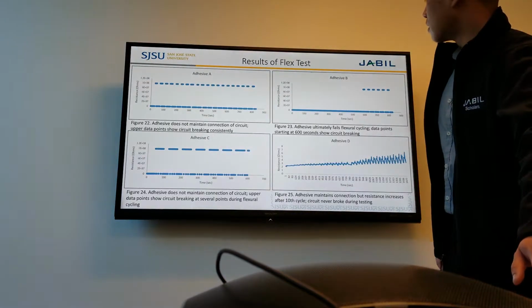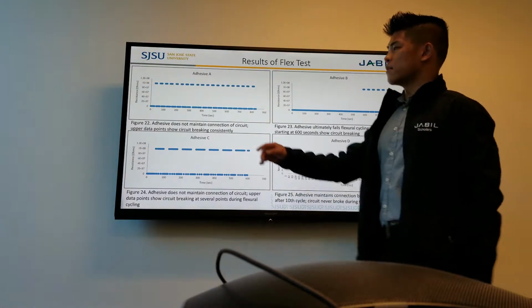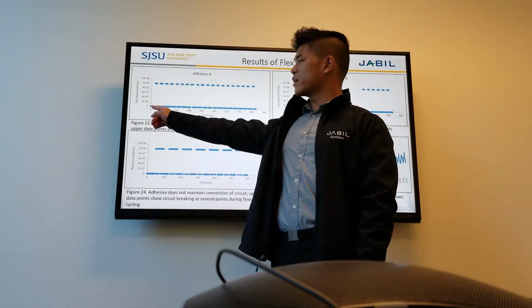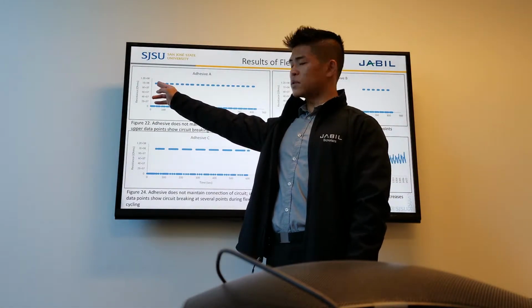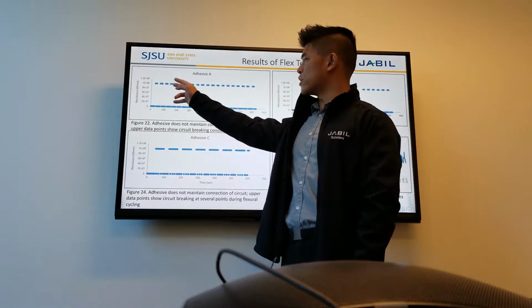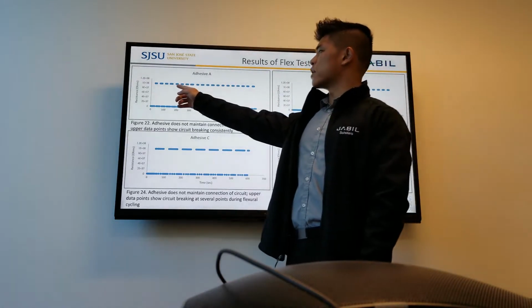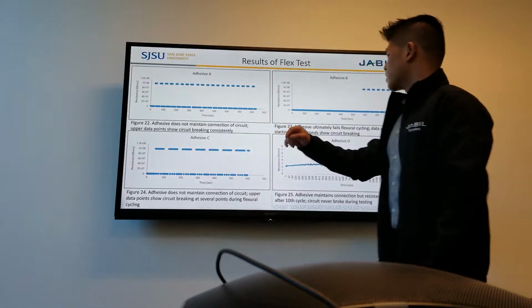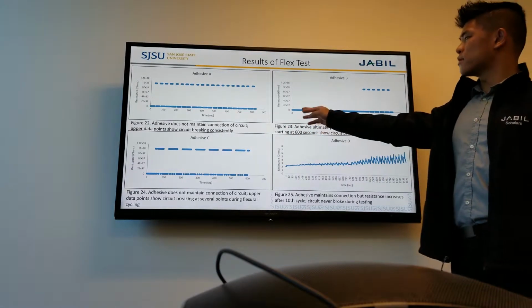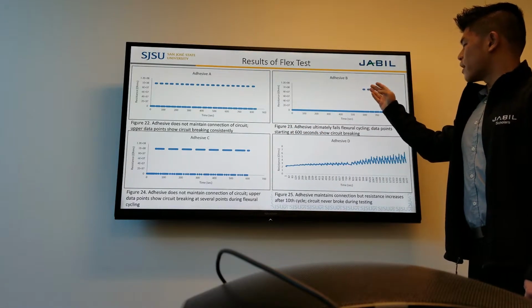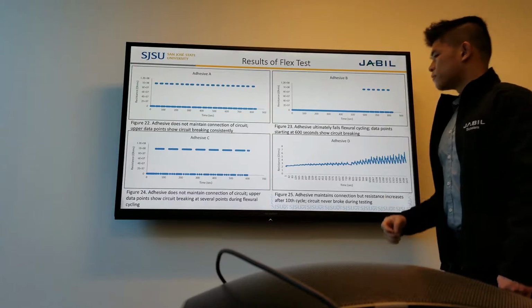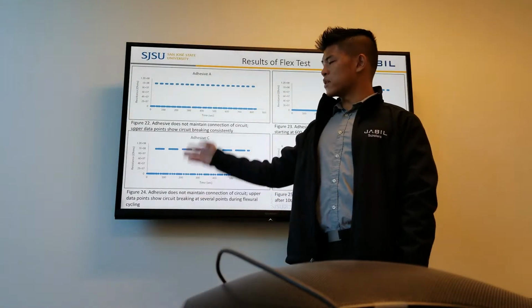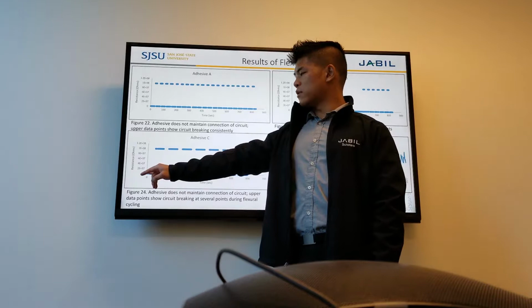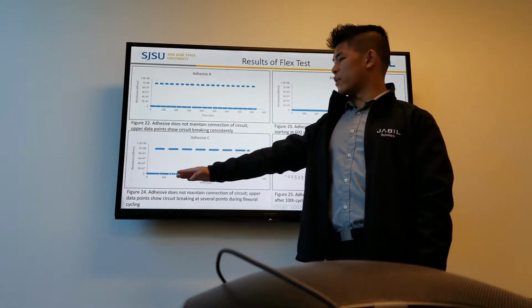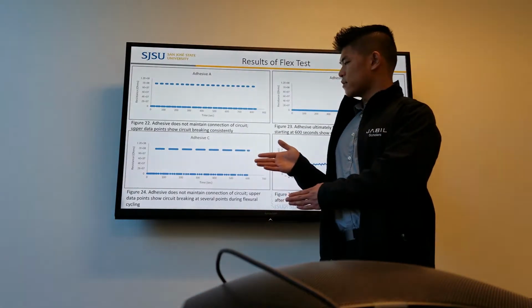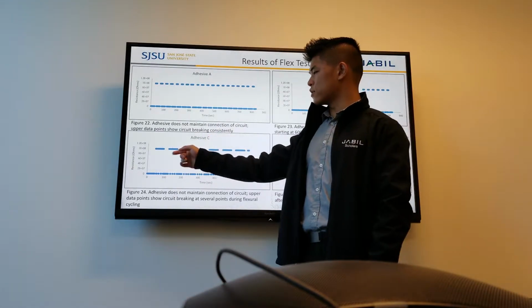And here are the results. Adhesive A starts with the circuit intact, and then within the first bend cycle, the circuit breaks, and it repeats over time. So each of these little dots on top is the circuit breaking. Adhesive B looks promising at first, the circuit didn't break, but then it breaks at the end of the 10th cycle. Adhesive C had the same results as adhesive A. It would maintain the circuit, and then it breaks, and then it maintains the circuit again once the circuit is flat. And then as the weight cycles through, the circuit will break.